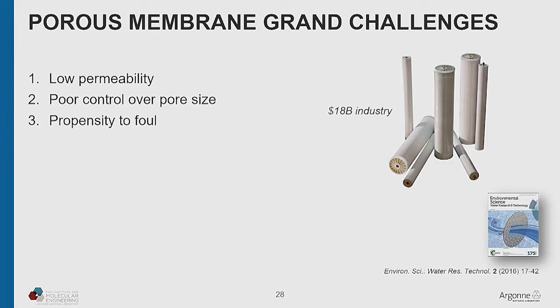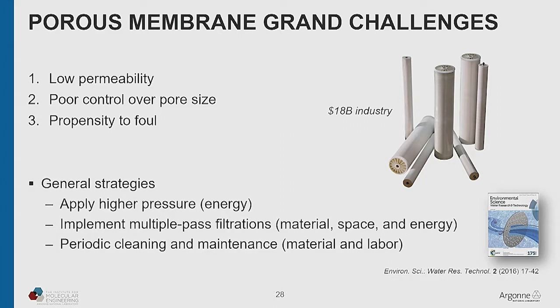And a universal challenge, not just with membranes, but in fact with pretty much any component in a water system, is fouling. Stuff sticks on the surface, and it can be biofilms, it can be organics, it can be scaling, all kinds of things can get stuck on the surface, and it's particularly a problem for a porous material like a membrane because those foulants plug up the pores, and then it doesn't work anymore, or you have to push harder. So what happens today is if you have low permeability, well, you just push hard enough to get your stuff through, and there's, of course, an energy cost associated with that. If your pore sizes are very diverse and stuff's getting through that you don't want to, say pathogens, well, then you can do things like multiple pass filtrations, and of course, there's a big cost associated with that as well.